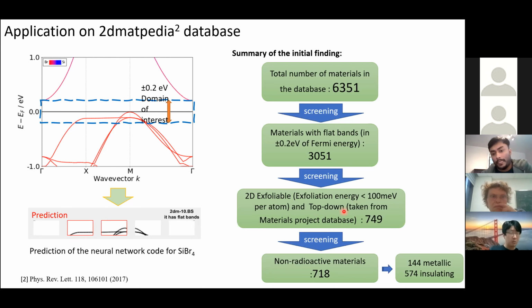And then we still filtered. Because we are working with 2D materials, we should have exfoliable materials, so we filtered out materials which have very high exfoliation energy, and we also filtered out radioactive materials, and we are left with around 720 materials, out of which around 150 are metallic.